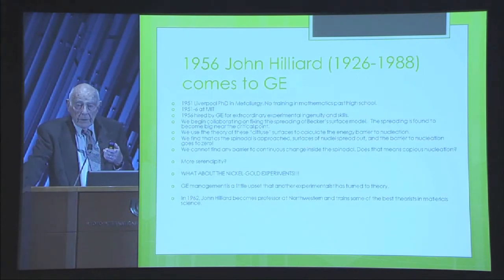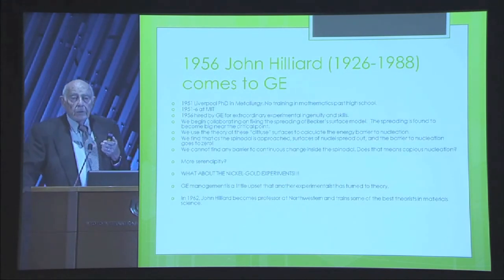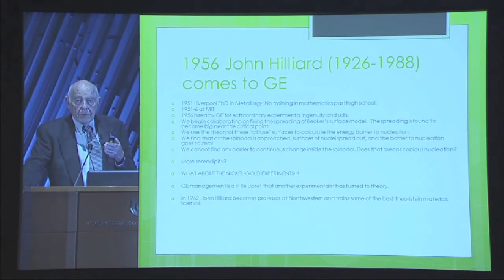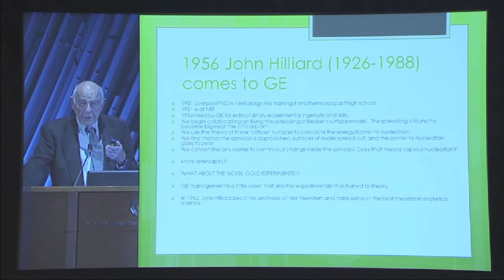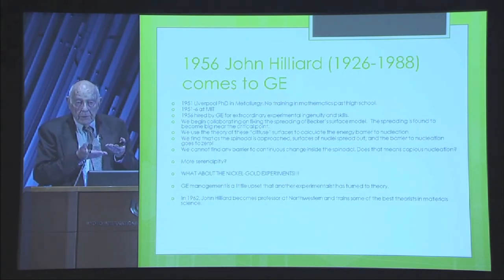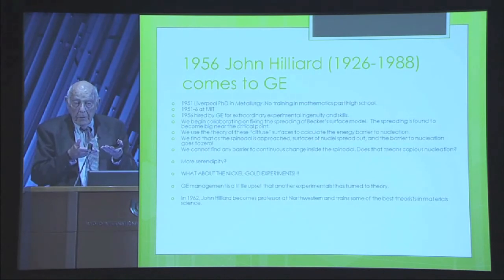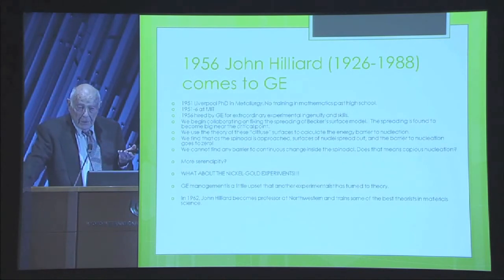And the theory of surfaces that we were using was a funny theory which had been first proposed in 1805 and rediscovered many times since, and it was a fallacious theory. If I look at the density of two fluids on either side of a surface, I can take the difference in density, and that's a number. I can multiply it by itself, that's the square, and the surface tension, according to this 1805 theory, was supposed to be proportional to that. Well, if I make two surfaces, each with half the density difference, then that would have a quarter of the energy, so the two together would have half of the energy of the previous one, that would be less in energy than a single jump.